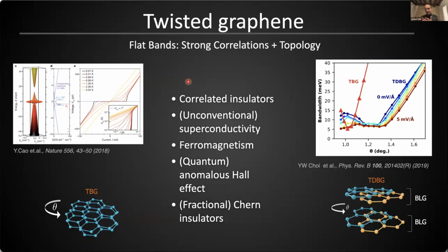So the point is, building on twisted bilayer graphene, you now have the added tunability of that starting band structure. You can now tune it with an electric field, and then you add the twist, and so then you have two of these right next to each other in momentum space, and they hybridize, and so then you can play your games. So one big advantage of twisted double bilayer, in addition to just this general tunability, is that there is no single magic angle, unlike twisted bilayer graphene. So there's a whole range of angles over which you can get flat bands.